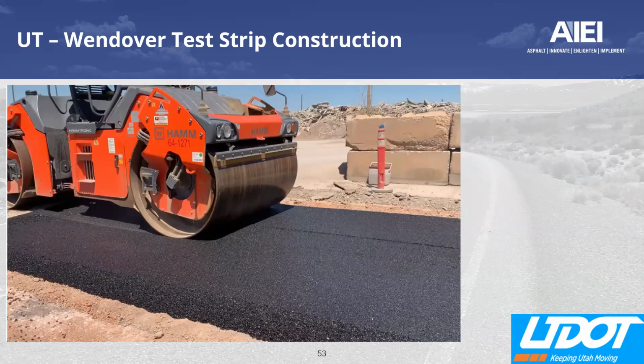You can give it a first shot and then I'll follow up, Dave. Yeah, one of the things to keep in mind is this is fairly new technology, going to these higher loadings of polymer. So the most that I can talk about is recycling of typical polymer modified material, which has a long history of success. We'll have to wait and see on the highly modified as to how that may or may not be any different. I don't anticipate that the need to recycle it will be as much because of the longer performance life. The other thing I would point out is that these are very rich materials, and recycling richer materials tends to be done more successfully than drier materials. And so I don't anticipate notable issues with that.